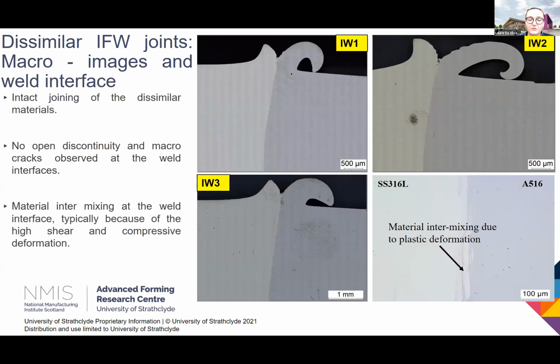And these are the results that we found. Looking at the macro images, you can see that we have intact joining. There's no open discontinuity or macro cracks observed at the weld interface. There's no cracks at the weld notch at the base of the flash here. You can see that there's nice intermixing between the stainless and ferritic steel due to the mix of shear and compression deformation that they'd be experiencing. And you can see there is a slight difference in the ferritic steel flash formation with increased friction and forge pressure. There's not that much difference in the stainless steel, as you would expect, due to its high temperature strength.